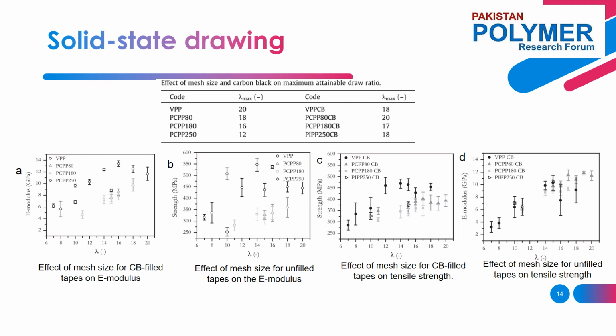The effect of mesh size and carbon black is presented in the table. It can be observed that for Virgin PP, the addition of carbon black results in a reduced draw ratio. By the addition of carbon black, the maximum attainable draw ratio is lower since this acts as a contaminant. The addition of carbon black to recycled isotactic polypropylene shows the opposite effect.